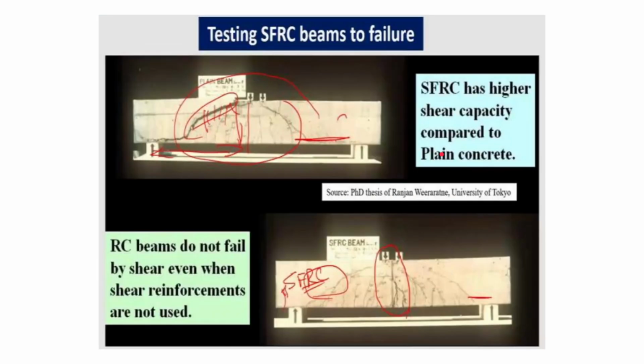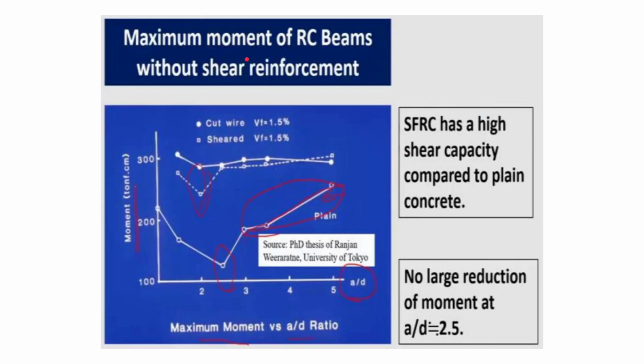Okay, now maximum moment of RC beams without shear reinforcement, if you see the two above cases of reinforced concrete, fiber reinforced concrete, one is cut wire and one is sheared. Okay, so both are having higher moment as compared to the plain concrete. And you can see that here in the plain concrete, when the A by D ratio, that is the shear span by depth ratio, is 2.5, there is large reduction of moment, but that is not found in the fiber reinforced concrete. Although in shear some reduction is found around 2, that is not that high as compared to this one.